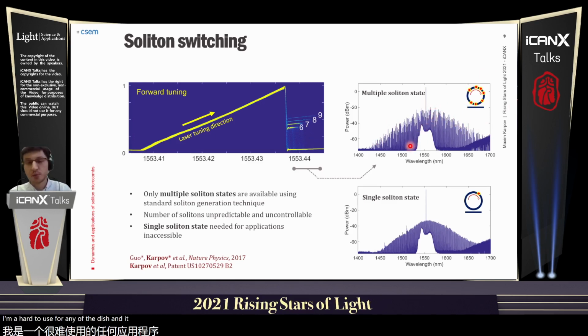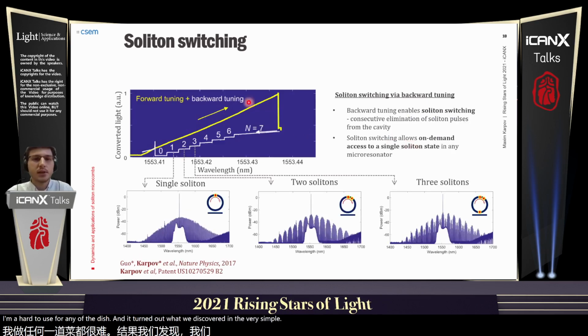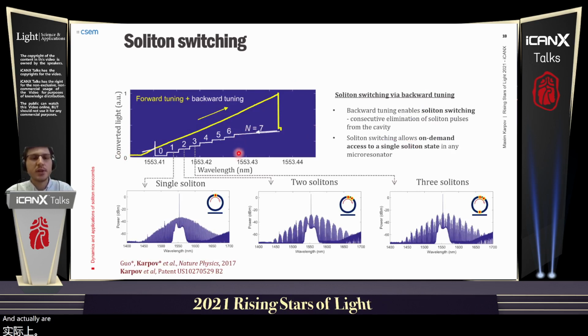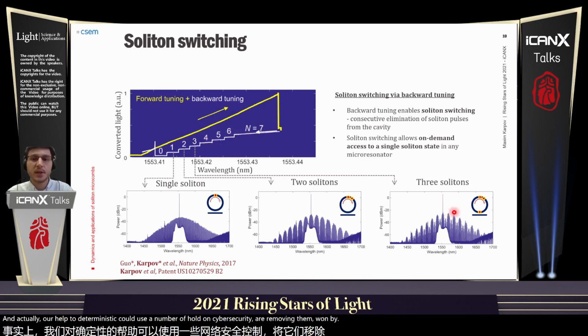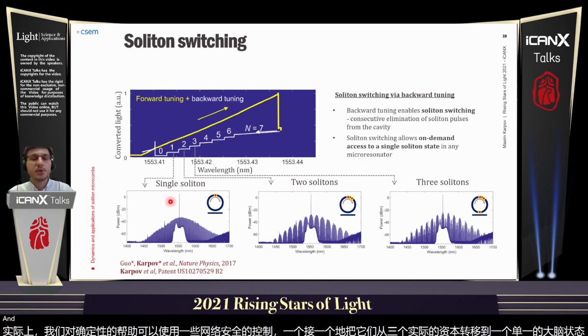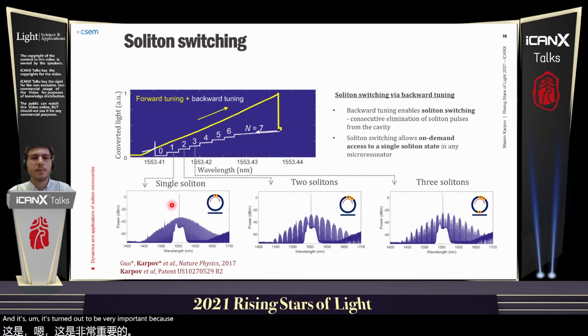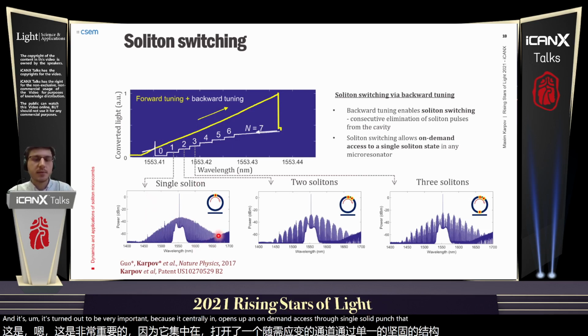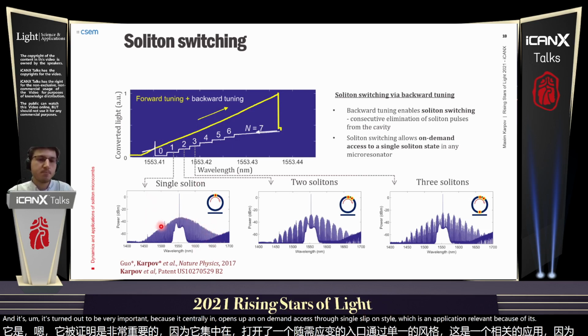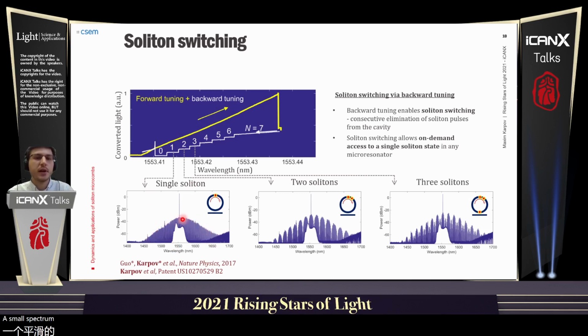And it turned out, what we discovered is that a very simple technique of adding an additional tuning step in the reverse direction can actually help to deterministically reduce the number of solitons inside the cavity, removing them one by one. As shown here, we go from three to two to a single soliton state. And it turned out to be very important because it essentially opens up on-demand access to a single soliton state, which is application relevant because of its smooth spectrum envelope and very low line-to-line variation.